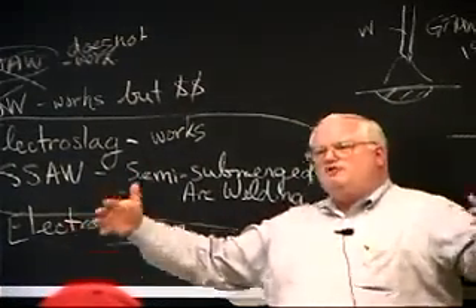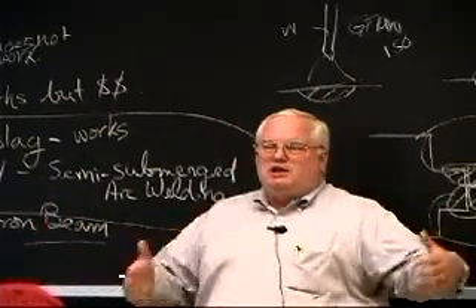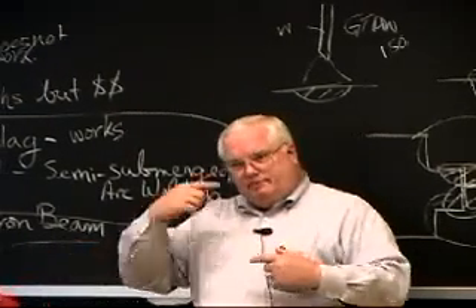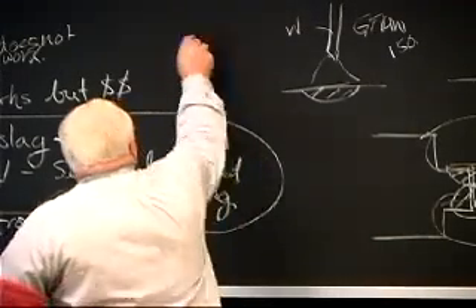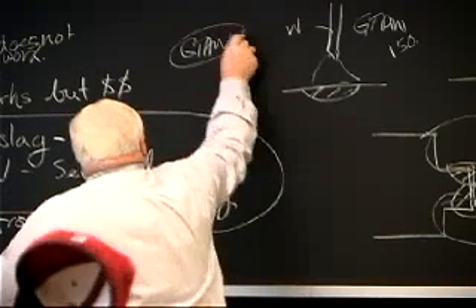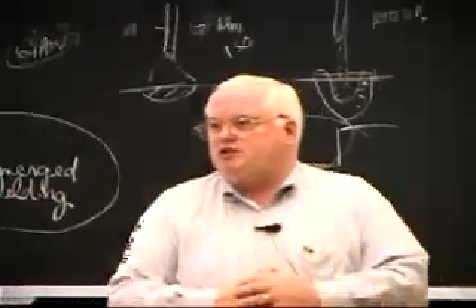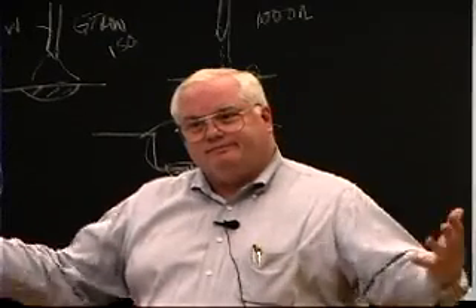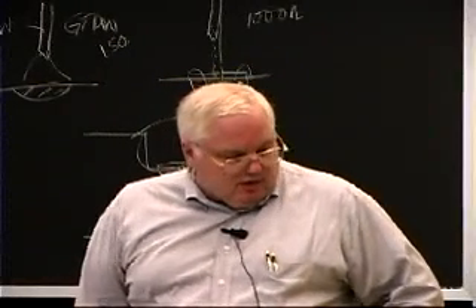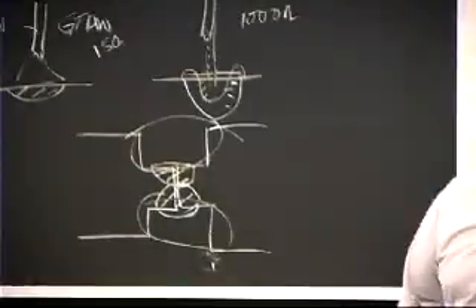And most of what they did, since we're only talking 4 feet in diameter, you could go to electron beam vacuum furnaces in the aerospace industry and build up a bunch of these things that you would then finally put together by gas tungsten arc welding, which also works, but is very slow, okay? And that's how they built these. The first one was built in 6 months, okay, by just using aerospace technology, if you will. Problem is, you're limited to about 4 feet in diameter. Okay, so there's only so much you can do on those. But so the Navy has built titanium submersibles. Actually, that was by DARPA.